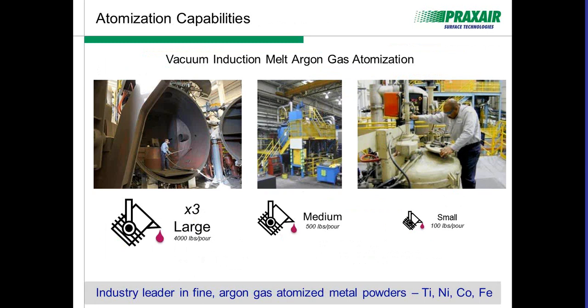When we look at yields, of course they're going to be optimized based on our customers' requirements. One of the keys is not to push the particle size too fine, because with additive there's typically what we call the bottom cut, the lowest particle size they'll accept in these machines. Typically that's between 10 and 20 microns, and on average around 16 microns. Then we want to control the upper end of that size range, which could be in the 53 to 45 micron range. Holistically, we're looking to maximize the yield of 45 on 16.